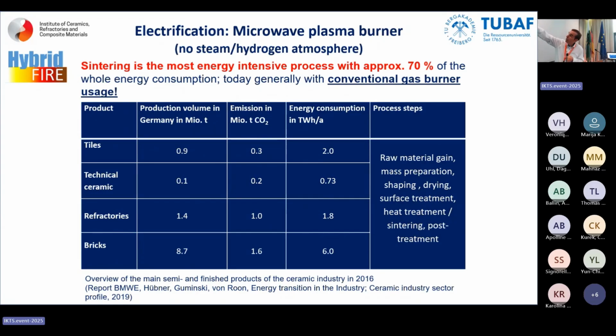Why? Because sintering is the most energy intensive process with approximately 70% of the whole energy consumption. And keep always in mind, if you have a tunnel kiln, only 10 to 15% goes to your component. Everything else are losses.